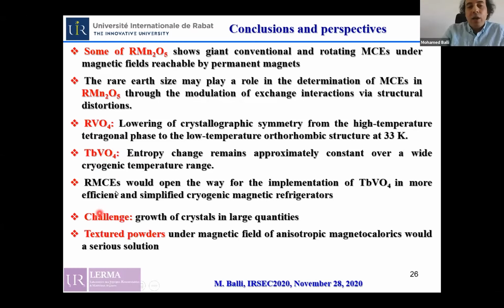Also, these materials show a high level of rotating magnetocaloric effect in the temperature range under 50 Kelvin, opening the way for their implementation in more efficient, compact, and simplified magnetic coolers.